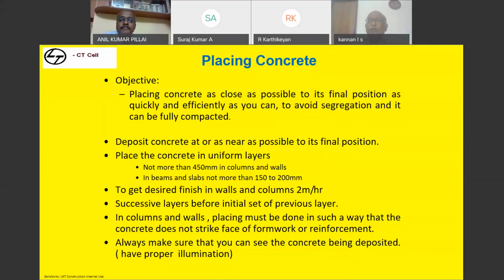For this, one test you can do is in the lab. The other thing, depending upon the site condition, is to make a 300 by 300 block. Keep on vibrating the block with a needle, either a 40 mm needle or a 60 mm needle. Just find out till what time you are able to close the hole when you remove the vibrator needle. What is the time from your beginning to the closing of the hole? Within that time, the concrete needs to be placed. This is a more practical scenario with which you can operate at site.